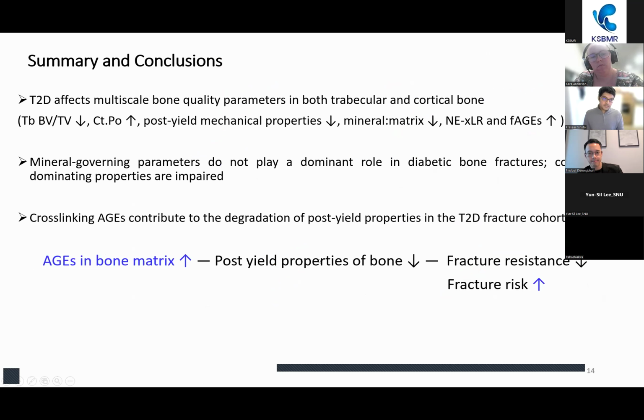With this, I would like to summarize that we found lower BV by TV for trabecular bone, increased cortical porosity, lower post-yield mechanical properties and mineral to matrix ratio, as well as increased glycation content in terms of non-enzymatic cross-link ratio and FAGE for both trabecular and cortical bone. Another thing, the mineral governing parameters do not play a dominant role in diabetic bone fractures, whereas collagen dominating properties are impaired and lead to fragility fracture in the diabetes cohort. Cross-linking AGE contribute to degradation of post-yield properties in type 2 diabetes.